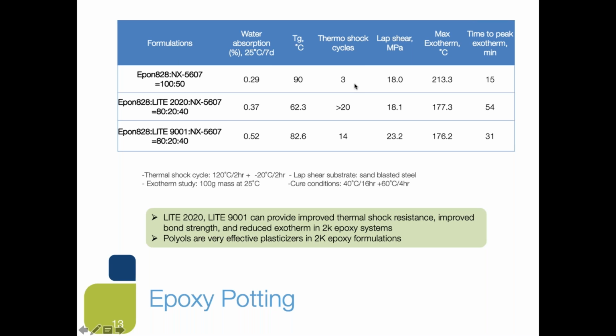significant improvement in thermal shock cycle. This thermal shock cycle was 120 degrees C for 2 hours, and then going to negative 20 degrees C for 2 hours, and repeating those tests until you see the failure. So you can see this much better performance. At the same time, we also achieved good adhesion strength, lap shear strength, and reduced exotherm, and then of course the longer